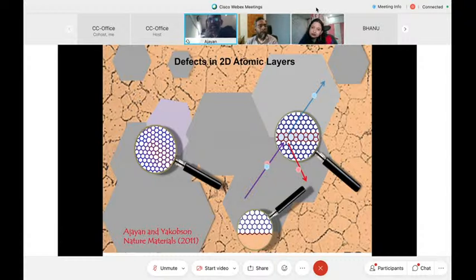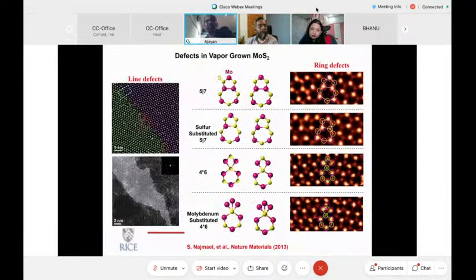I'll show you a couple of images. This is actually from molybdenum sulfide. And you can see the grain boundaries have these topological defects, which are different from the 6-member rings that you see in the lattice. And these defects are also very interesting, especially in these two-component systems, because then you end up with sometimes sulfur deficiency at the grain boundary. And that changes the electronic structure. In fact, people have even measured magnetic properties of these grain boundaries because of the electronic structure change at these boundaries.